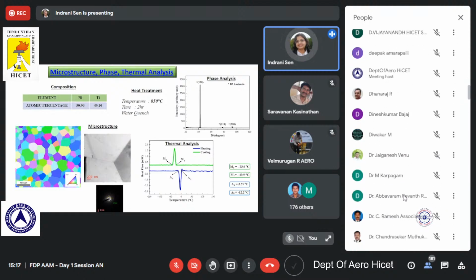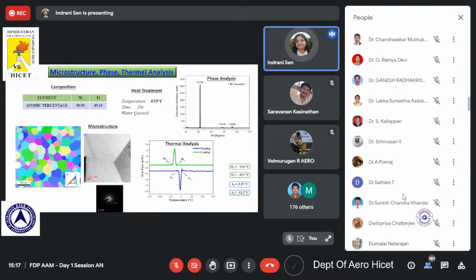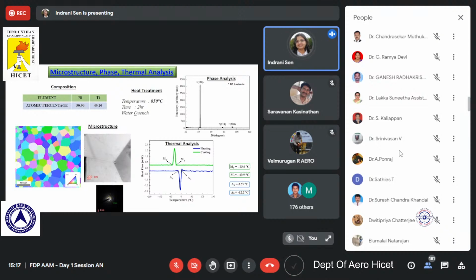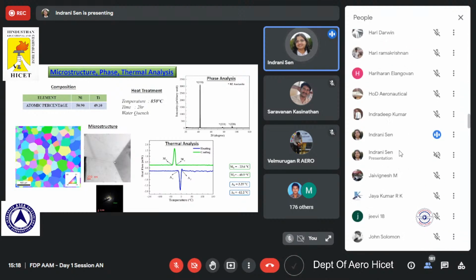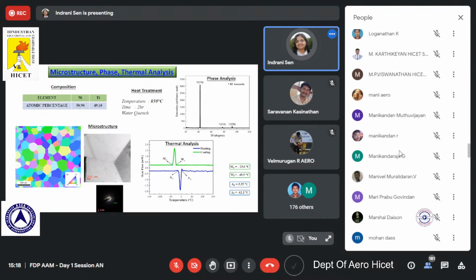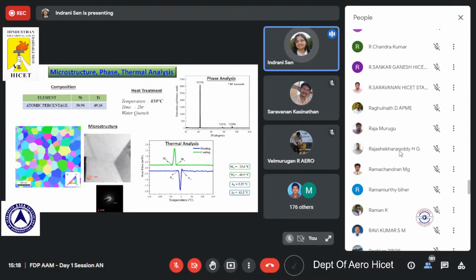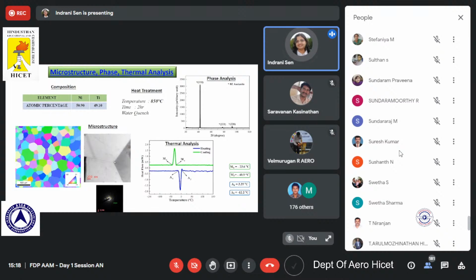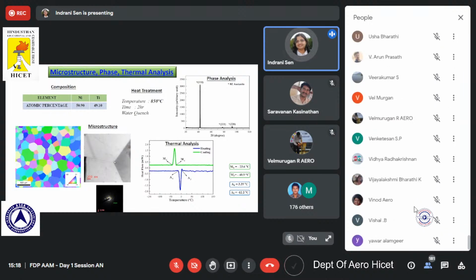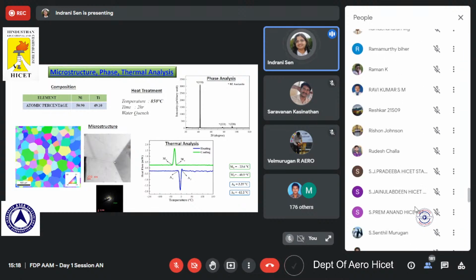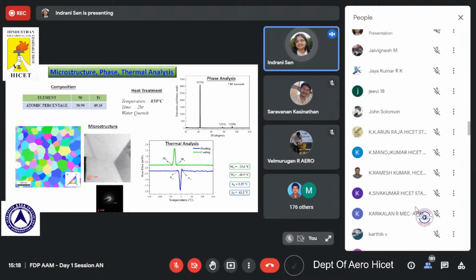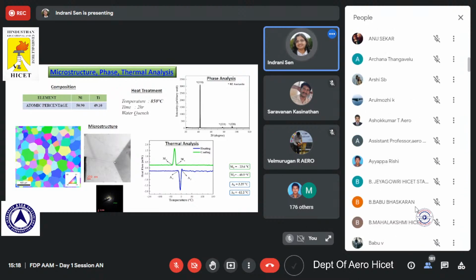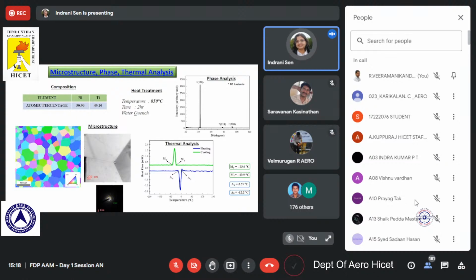This is the TEM image, and you can see the grain boundary and the triple points here. The crystal structure of the austenite phase is confirmed through TEM, and we are satisfied that this is a single phase material. This is also confirmed by the XRD, X-ray diffraction, which shows a single phase material with the austenite structure having the B2 phase. This B2 is just the ordered cubic structure.